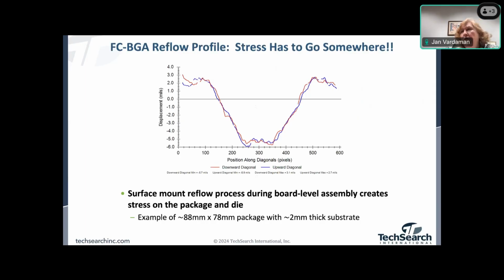So one of the questions that we need to look at is, if you do this as a BGA, when you mount the BGA on the board, you have a lot of stresses that are created. During the surface mount reflow process, you've got stresses on both the package and the die. This is an example of an 88 millimeter by 78 millimeter package with a 2 millimeter thick substrate. And as you go through that reflow process, you can see what the profile looks like. So this is going to go through a frowning, a smiling, all kind of different positions. So that stress is going to go in places that you don't even know about.